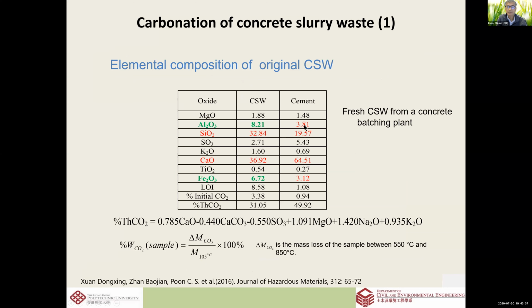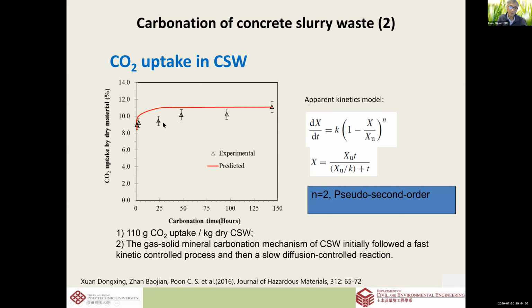This is not similar to cement. CSW contains a lot of silicon dioxide, it contains PFA, and the silica fume content is higher than that of cement. The silicon dioxide and aluminum oxide are higher than in cement as well. But it can be carbonated. This concrete slurry waste can be carbonated, and when we carbonate it, it takes up about 10% CO2 in terms of cement mass.